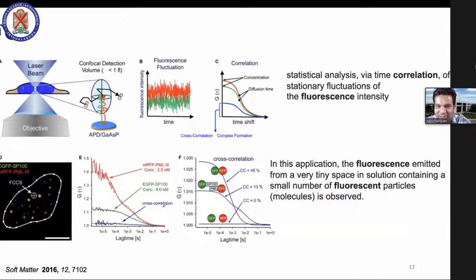How do we observe? This is the basic idea of fluorescence correlation spectroscopy. This is how it looks. We have a confocal volume. This is a one femtoliter small volume, and you use the polymer brushes or the polymer in solution, excited at a given wavelength. The fluorescence fluctuates, which gives the fluorescence intensity, related to the number of particles and the diffusion time. You can measure the diffusion time, and it also provides the concentration of the particles present in the excited region.